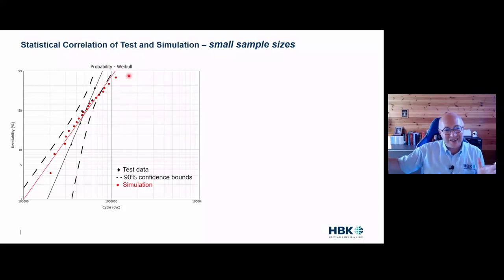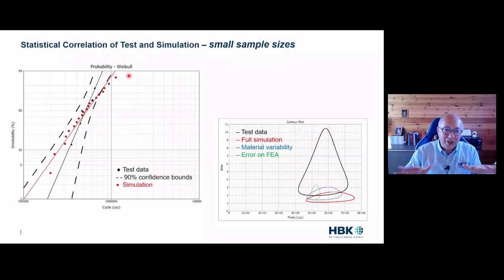So in the high cycle end, maybe our simulation isn't as good, but for most of it, it works tremendously well. Now, as well as that, we can look at the contour plots. So what's a contour plot? We know that a Weibull analysis has 2 parameters, beta and in this case theta. Now, with a 90% confidence, our tests' beta and theta lie somewhere within this contour here. And again, at a 90% confidence, our full simulation is in the red. And the fact that the black and the red curves overlap is telling us that we can accept this simulation at the 90% confidence level.